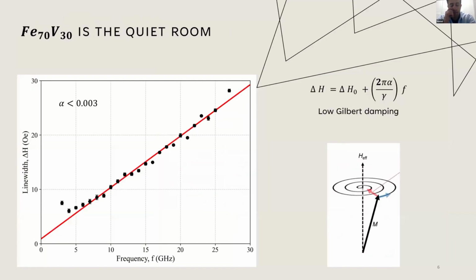We did measurements for a 25 nanometer iron 70 vanadium 30 sample, and we plotted the line width for different frequencies, and we got this straight line. If we fit these data points by the Gilbert damping relation, we get a Gilbert damping constant smaller than 0.003, which indicates that our iron vanadium is very low damping, and so we can say that our quiet room is ready now.